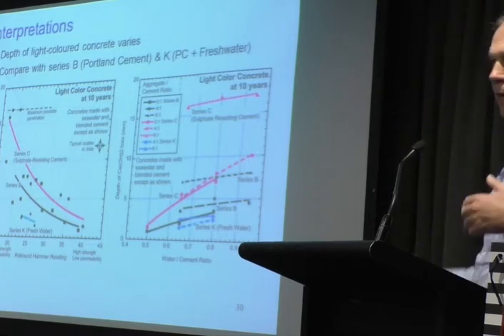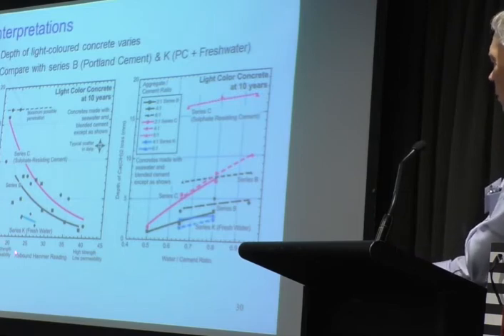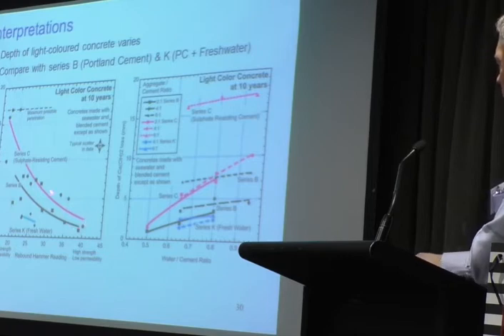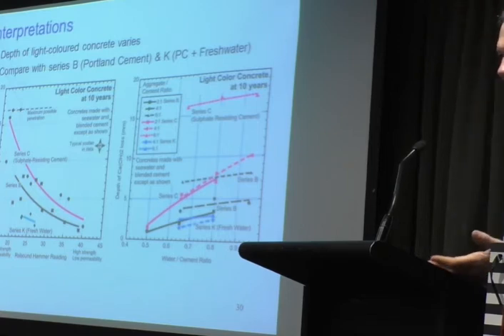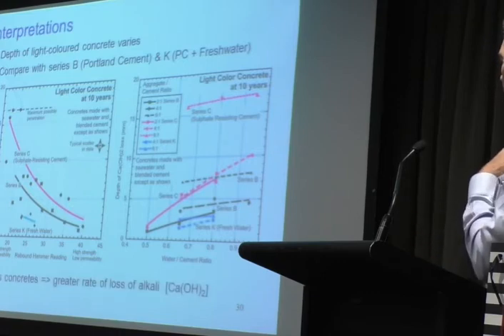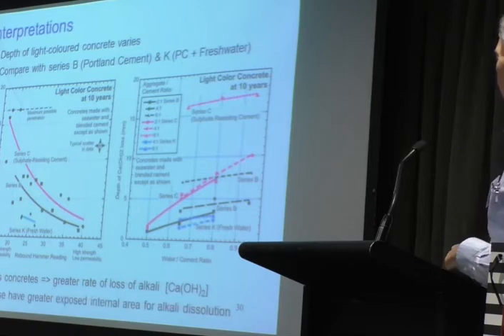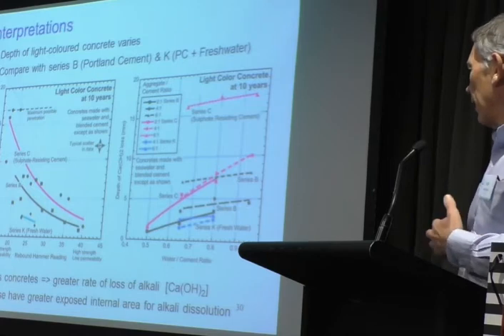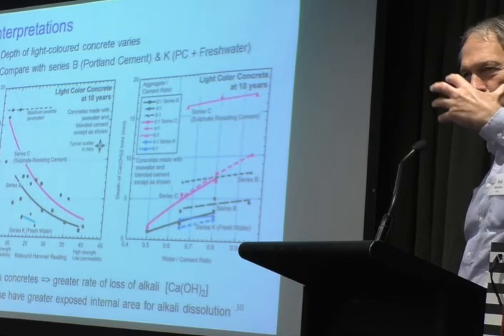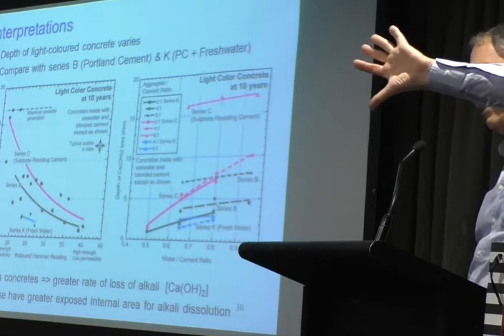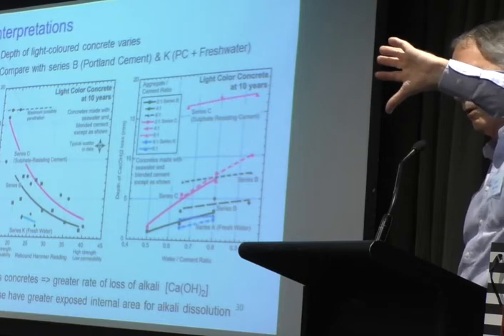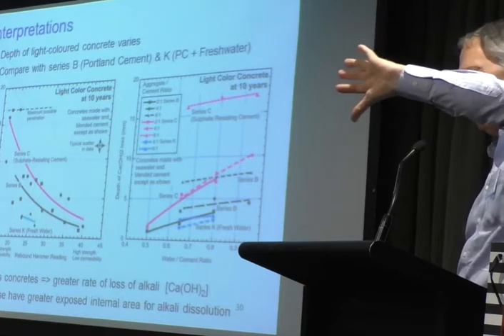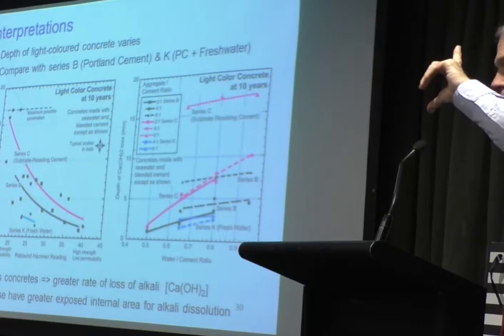The depth of penetration of that light zone is much greater for the high permeability concretes compared to the low permeability concretes. And for fresh water, not much is happening. For the B series, which is a standard Portland cement mix up here, sulfate-resisting cement actually isn't all that great, as we now can see, but it did unlock, if you like, the reason for what we're seeing. So the porous concretes have a greater rate of loss of alkali, and of course it doesn't help because the internal exposure of the alkalis will be greater if the concrete is more porous. So it's a dissolution of the alkalis, that's the important bit. And that we know is increased by sodium chloride.